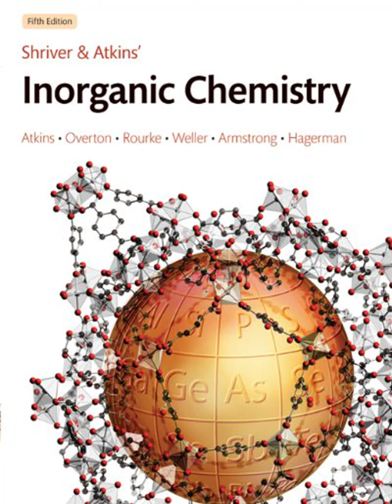So researchers are looking at materials that chemically bind hydrogen, metal hydrides. Like magnesium hydride. MgH2 is a good example. It stores a decent amount of hydrogen by weight, about 7.7%, but you have to heat it pretty high to get the hydrogen back out. People are trying things like doping it or grinding it into nanoparticles, ball milling, to improve that.